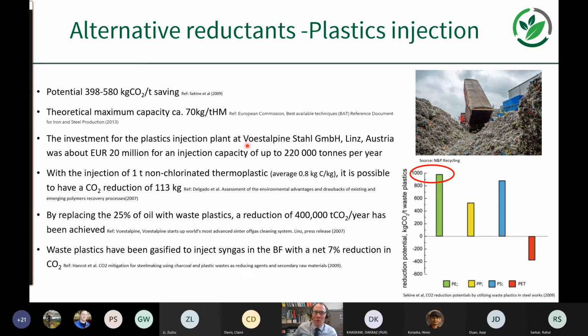So what I've been looking at more recently is the use of plastics and potentially biomass paper in reducing the CO2 emissions. And the importance of this is that potentially there's room to improve the CO2 emissions from plastics injection. So not only are you repurposing the blast furnace, not only are you utilizing material that otherwise might find its way into landfill, but you're also substituting, importantly, mined coal. And in the process, you're improving the CO2 savings per ton of hot metal, per ton of plastic that's injected into the furnace.